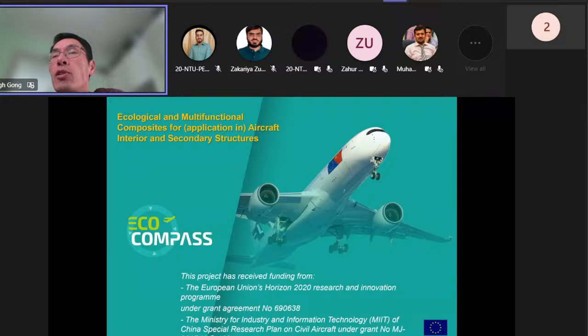We had a large project in collaboration with several European partners and also Airbus, and also with several Chinese research organizations, and also the manufacturer of, I think, the latest commercial passenger aircraft in China. The idea is to see if we can use recycled carbon fibers in aircraft and other transport vehicles. Again, as I mentioned before, the problem with recycled carbon fibers is that they tend to be short and random. And that means the mechanical performance in the eventual composite tends to be a bit of a problem. So we were trying to develop composites for secondary components in the aircraft. Things like seats, for example, and door panels.